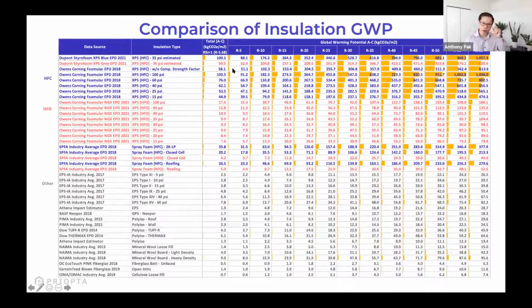So what I've mapped here is kilograms of CO2 per meter squared of insulation at various different R values from R5 to R60. So for example, for XPS, it's roughly R5 per inch. So this is 1 inch of XPS. This is 12 inches of XPS. And you can see there's big discrepancies, especially for XPS and for spray foam. These numbers get really, really high. These are almost on a whole building level, almost the scale of whole building emissions, if you recall what I showed you earlier, kilograms of CO2 per meter squared, right?